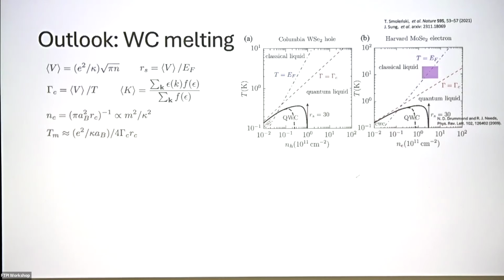So here is the mean field phase diagram of quantum Wigner crystal, which I was taught by Boris. There should be a dome of Wigner crystal in the temperature and density phase diagram. It should be understood as if you increase the density, then the quantum fluctuation increases and the Wigner crystal melts. If you increase the temperature, then thermal fluctuation increases and the Wigner crystal should melt. And you can estimate what the critical density and the critical melting temperature are in this kind of system.